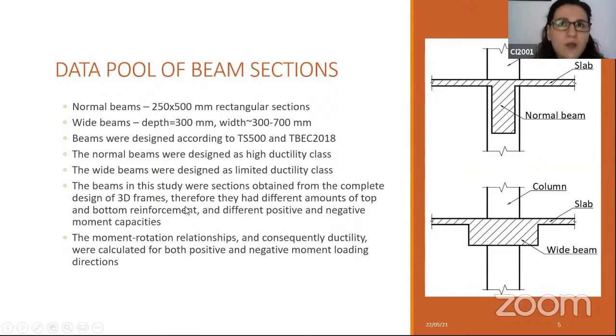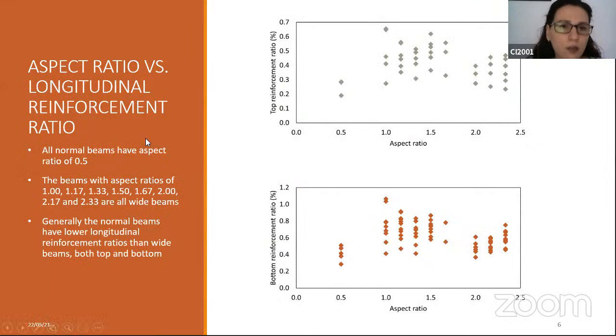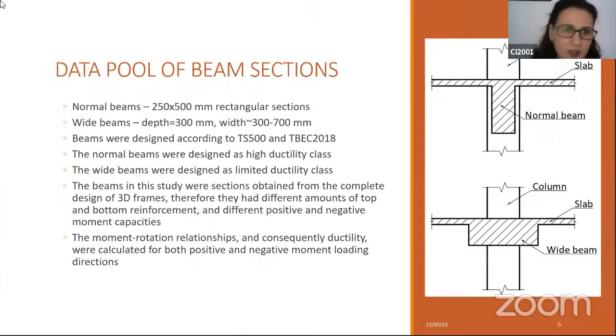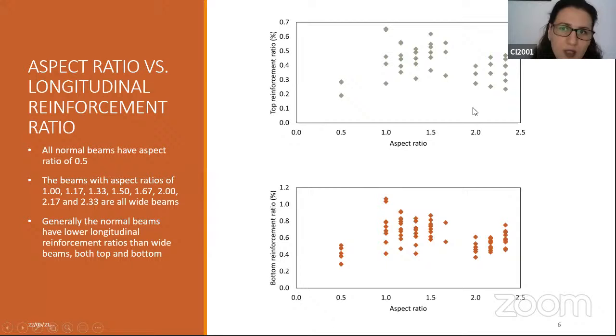As I mentioned, these beams were obtained from full frame design study. So they were designed for different load combinations, and different reinforcement ratios and different moment capacities were obtained for each of these. Before starting investigating the ductility, we wanted to observe the reinforcement ratios versus the aspect ratio. As I mentioned, the aspect ratio is the one parameter that we can directly correlate to the beam being either wide or normal. So all the normal beams, as we can see here, have an aspect ratio of 0.5, and the rest of the aspect ratio values indicate that they are wide beams.